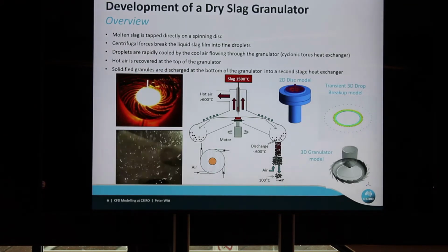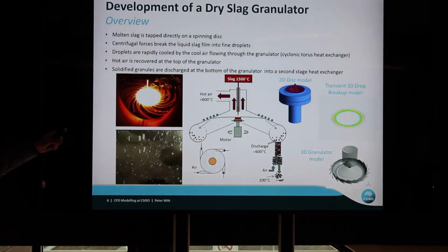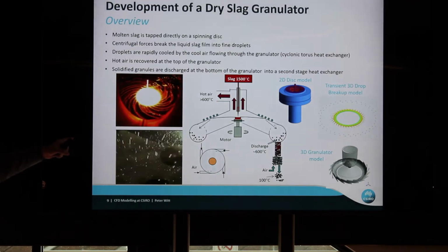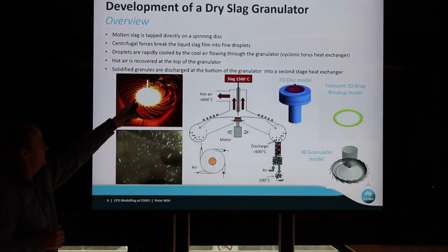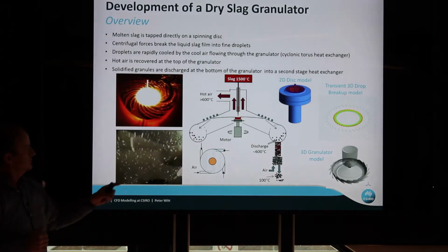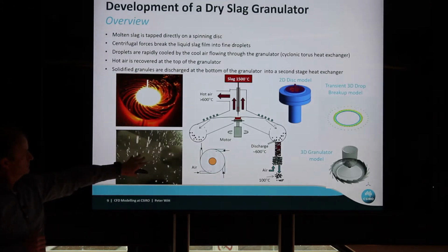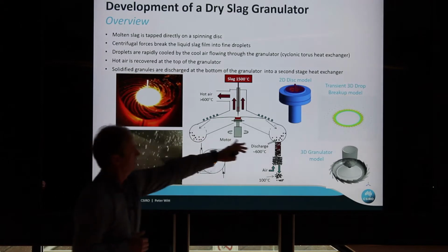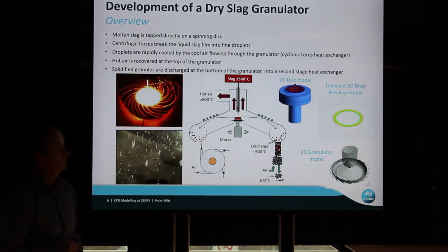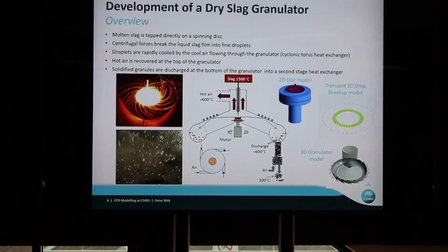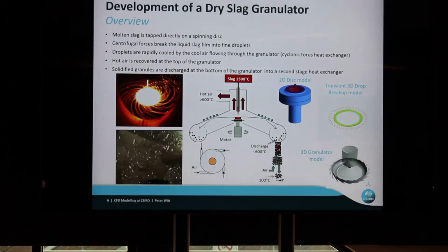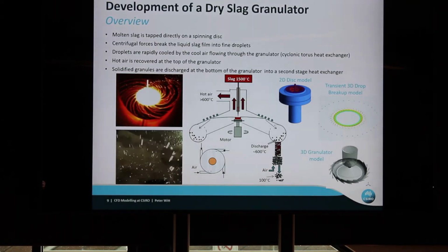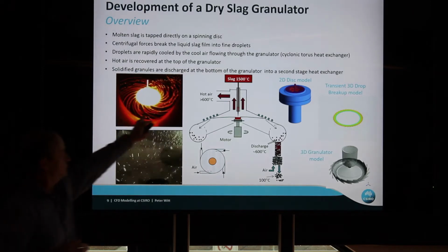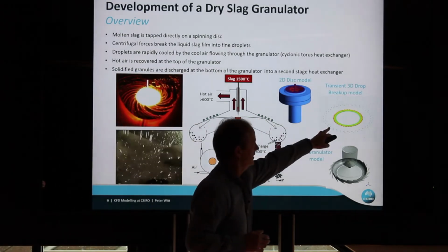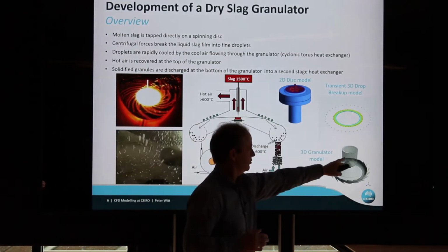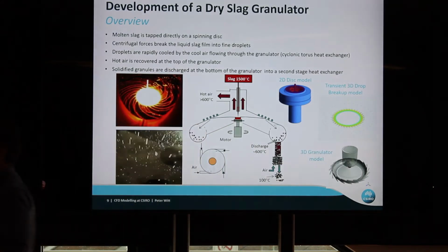So this is the conceptual design. You can see the slag drops in at the top onto the spinning disc. You can see how the disc spins, breaks up into ligaments and droplets. You end up with a whole lot of really hot droplets spinning around in this torus region, then they come out through the bottom. So for us, we broke it up into 3 CFD type problems, if you like. One, looking at the spinning disc, what's going on there. Another one looking at the breakup, and then another problem looking at what happens in the granulator.